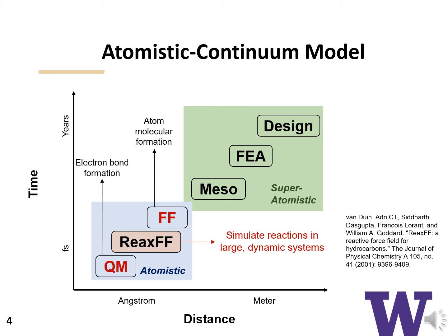ReaxFF is a reactive force field molecular dynamics simulation technique that uses the bond order concept to consider the instantaneous interactions between atoms. It provides a smooth transition between the non-bonded states and the bonded states, allowing one to investigate ongoing chemical reactions where bond formation and dissociation are involved during temperature simulations.